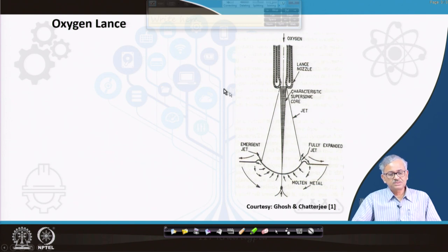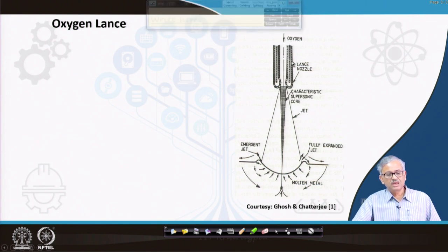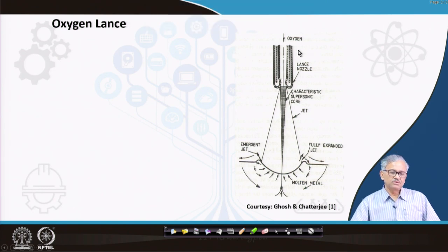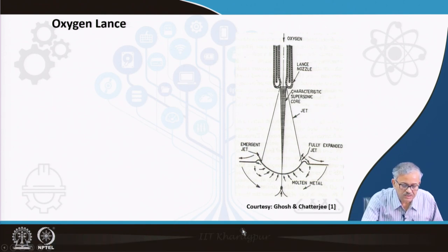Okay, now let us first discuss the oxygen lance. You can see this is the oxygen lance, and oxygen comes through this annular portion, and you can find here the cooling arrangement. Basically you have water flow, one inlet and one outlet, such that the nozzle tip is cooled. Another feature is that there is a special nozzle. It is not a cylindrical nozzle. You can find there is a convergent section and a divergent section. It's convergent and divergent.